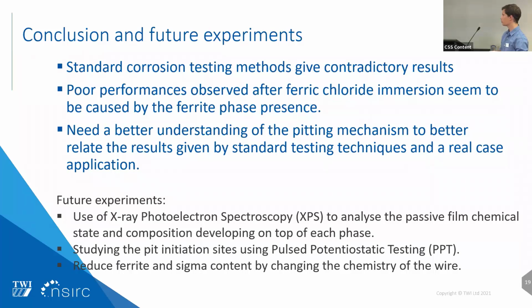We are also doing some potentiostatic testing, the goal of which is to initiate a large quantity of pits on the material, to see where those pits are initiating, and see if we can consistently trigger pits at the interface between the ferrite and austenite, or if we might have other initiation sites within the material.